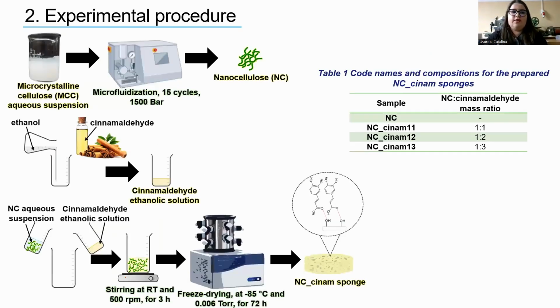In the first part of this work, we attempted the physical modification by non-covalent bonds of cellulose nanofibers with cinnamaldehyde, by simply mixing an aqueous suspension of nanocellulose, obtained by the mechanical defibrillation of microcrystalline cellulose in a microfluidizer, with an ethanolic solution of cinnamaldehyde, followed by freeze drying. The names and mass ratio between nanocellulose and cinnamaldehyde in the prepared sponges are listed in Table 1.